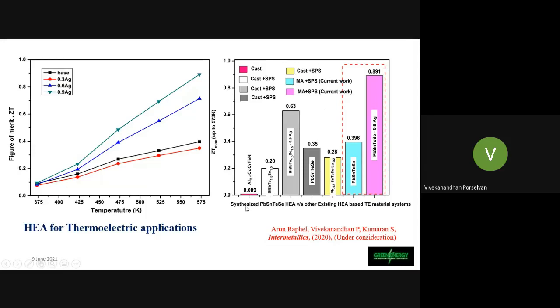So here the comparison is being made with different kinds of processes for PbSnTeSe alloys that are doped with 0.9 Ag. Here this particular alloy is showcasing a higher figure of merit of around 0.9. It is due to the synergetic effect of doping, which increases the electrical conductivity, and also the high entropy phenomena and nanostructure phenomena, which lower the thermal conductivity. As compared to other approaches like casting and SPS, mechanical alloying with SPS is so potential, as we all know that it is one of the rapid methods to retain the monophase as well as the finer nanostructure.